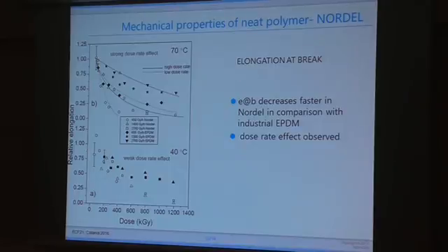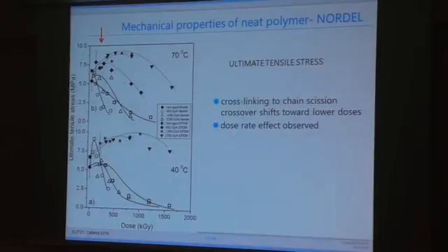Further on, if we compare elongation at break versus dose data, we can see that the open spots are for the neat polymer and the dark spots are for the industrial polymer. So the elongation at break decreases much faster in the neat polymer. And again, we can observe a dose rate effect, and it is much stronger at high temperature. Second, if we compare ultimate tensile stress data, we can observe that the crossover point from cross-linking to chain scission appears at lower doses in comparison with our industrial polymer. Again, the dose rate effect is still present in the neat polymer. This brings us to the conclusion that our neat polymer is much less chemically stable for the same aging conditions, and this is expected because the industrial polymer also has some antioxidants in its compound, and also a lot of additives that